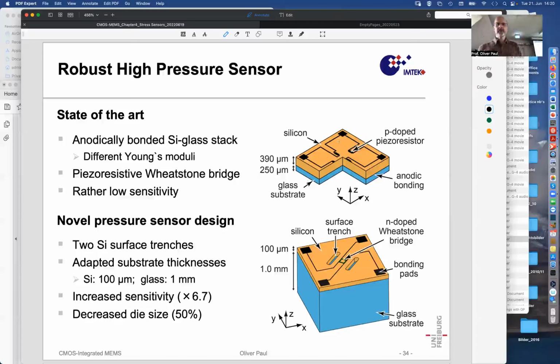And then the idea of that original work was to implement some piezoresistors on the surface to note that bending. And with the knowledge that we have now, probably we'll say it's amazing that the resistors are so much in the center. If they were totally in the center, because of the symmetry of the structure, of course, the stress in the center is isotropic. Sigma xx, under this bending, is the same as the bending in the y direction, sigma yy. And the action of the Poisson's ratio would be the same, also under 90-degree rotation. So there will be isotropic stress. Sigma xx is equal to sigma yy.